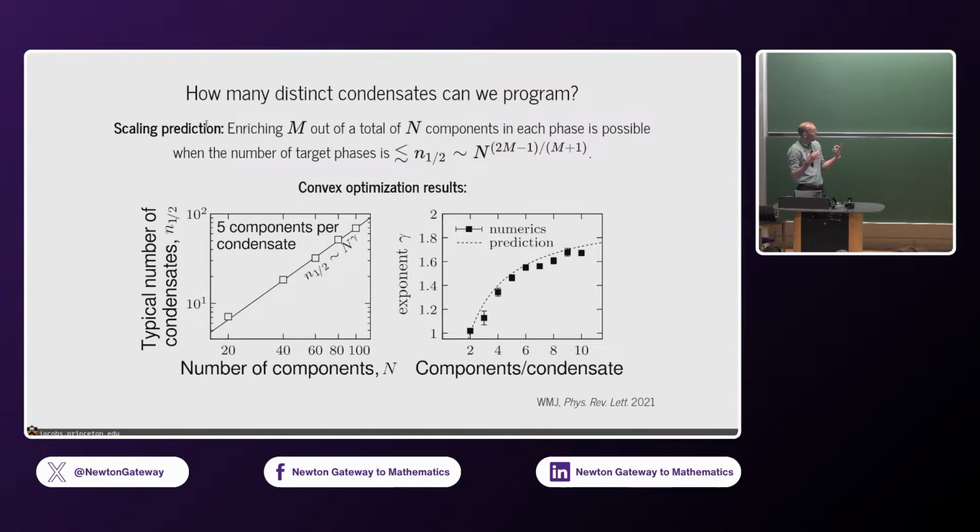Okay? And if this is surprising at all, that you can get a super linear growth in the number of phases with the number of components, seeming to maybe contradict Professor Gibbs, there's not actually a problem here. We're thinking again about local equilibrium, and we're simply trying to estimate the number of local minima on this very, very high-dimensional free energy landscape. And I'll show you in a little bit that this actually does work if you perform more detailed simulations.